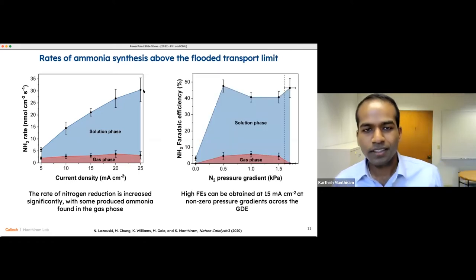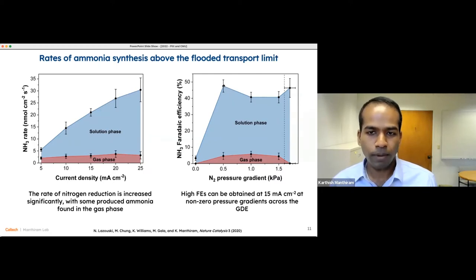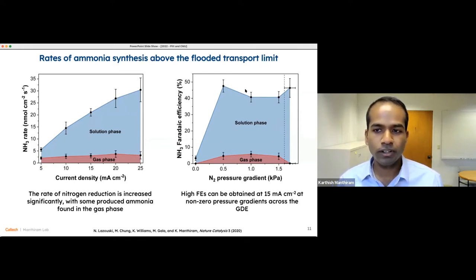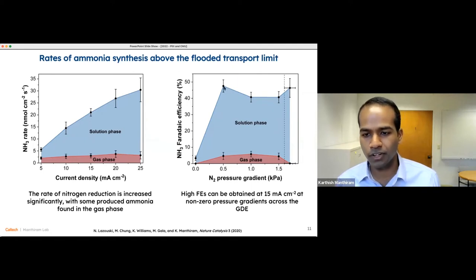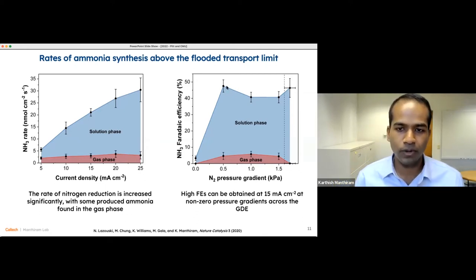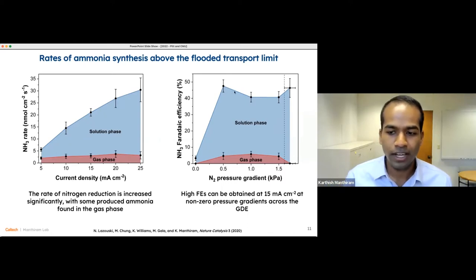And in addition, the Faraday efficiencies also benefit. So we can get to a point where about 40 to 50% of the electrons are going towards making ammonia with a modest pressure gradient. There's actually a large window here of robustness. So irrespective of whether you're at half a kilopascal or 1.5 kilopascals, you actually get very similar and stable performance when it comes to the ammonia synthesis Faraday efficiency. So now nearly half of the electrons are going where we want them to.